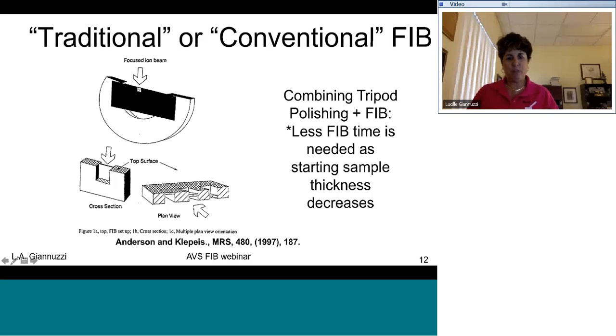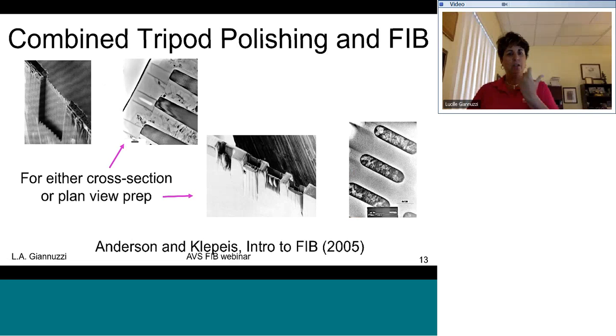Similarly, if you have a plan view prepared sample, that is a sample that's just polished at 90 degrees with respect to this sample, I can then make FIB windows of, let's say, this is the bread, this is the tomatoes, this is the cup hole, etc. You can make FIB samples of different plan view regions throughout the one sample. So really advantageous to do it this way, and you really limit FIB time. Okay, so this is shown in the Intro to FIB book.